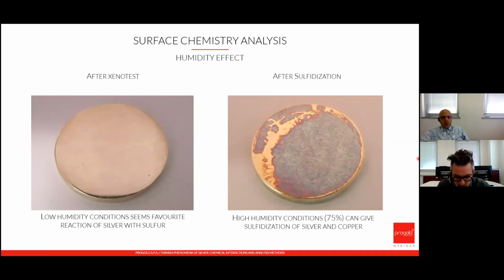Regarding the effect of humidity, for traditional sterling, it seems that low water vapor concentrations like those inside the ultraviolet chamber promote the sulfidization of the silver element alone, whereas high humidity conditions like those in the climatic box can lead to the sulfidization of copper and silver at the same time.